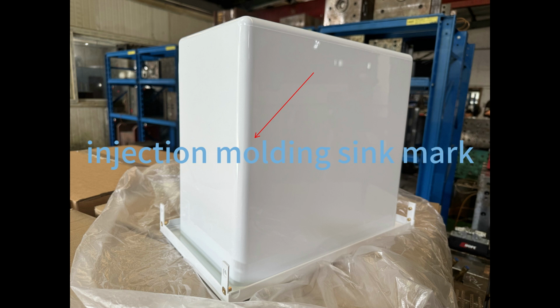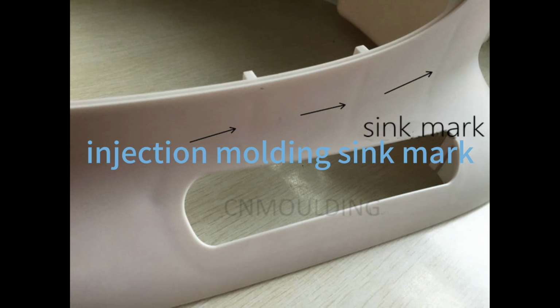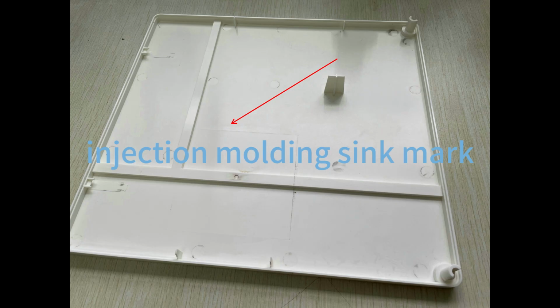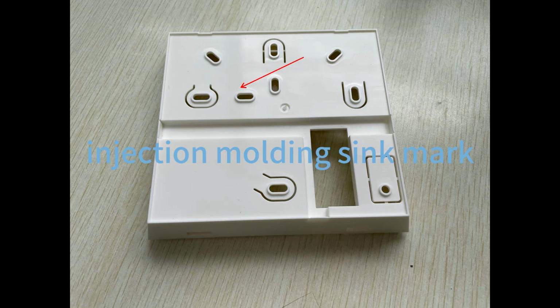How to prevent sink marks? Optimize wall thickness. Design parts with uniform wall thickness to ensure even cooling. If thick sections are unavoidable, use coring or ribbing to reduce material volume. Increase holding pressure and time. Apply sufficient holding pressure and extend the holding time to pack more material into the mold and compensate for shrinkage.